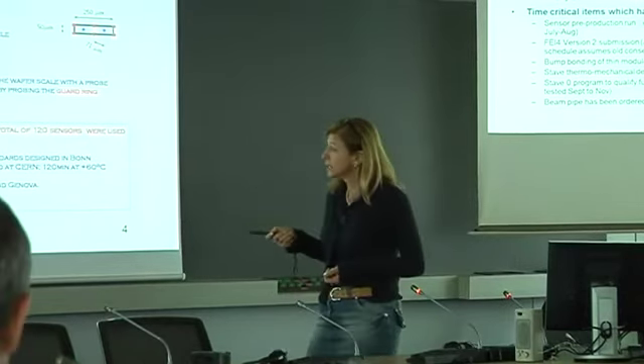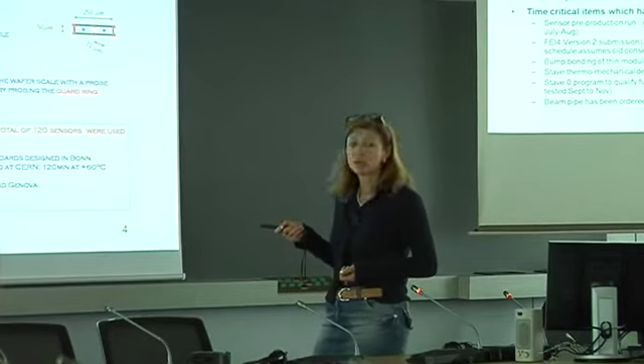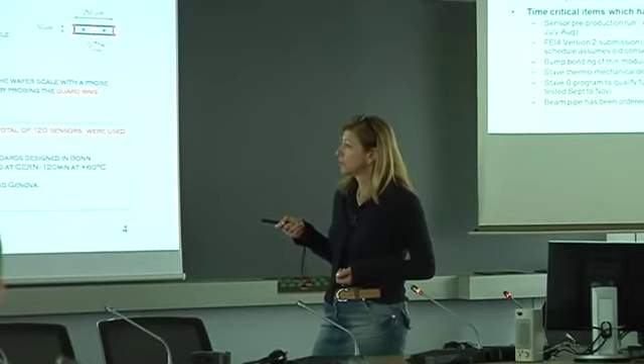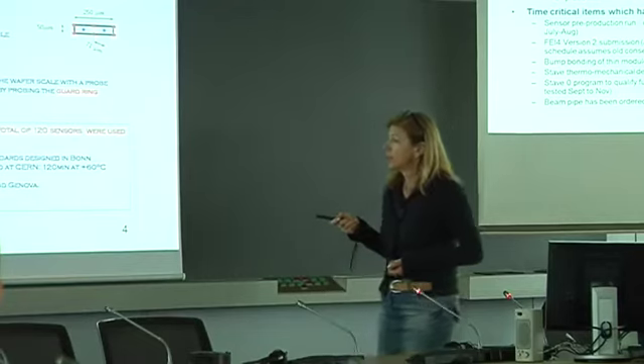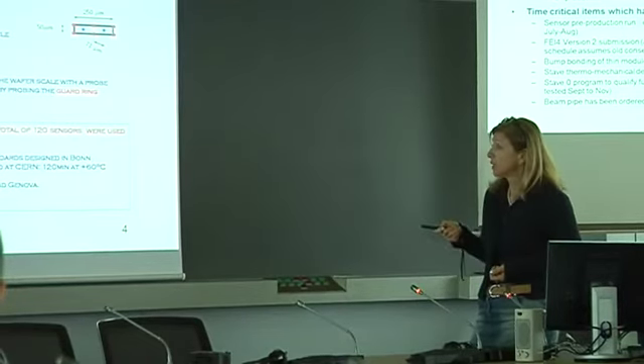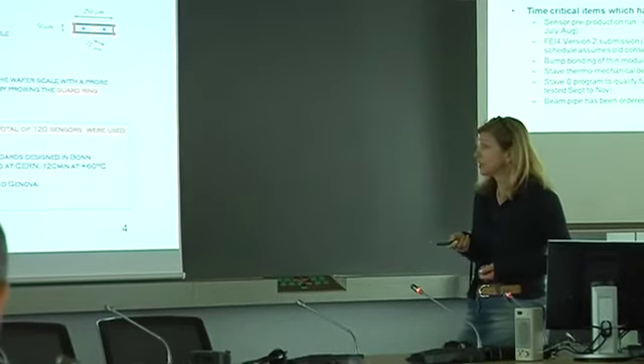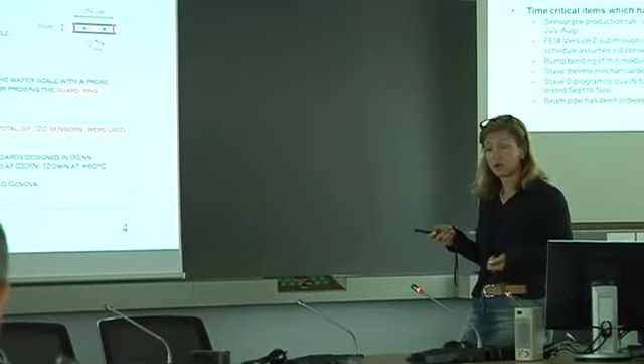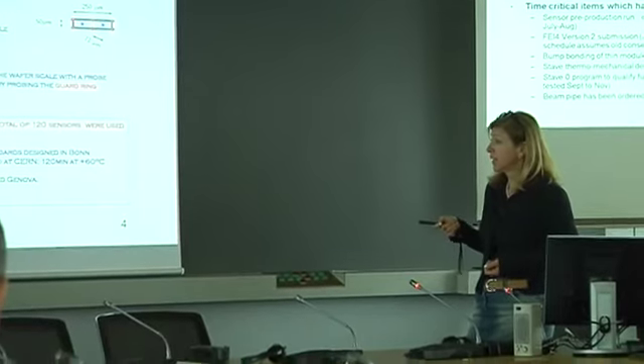And here is the list of what we used. So there were 32 wafers bump-bonded at IZM. They were mounted in Bonn, in Genova, and on boards designed in Bonn. 8 were irradiated in Karlsruhe and Ljubljana. Annealing was performed at CERN using the scenario that we agreed together with our PPS colleagues. Test beam is coming mainly from the CERN SPS with the qualification wafers and devices.